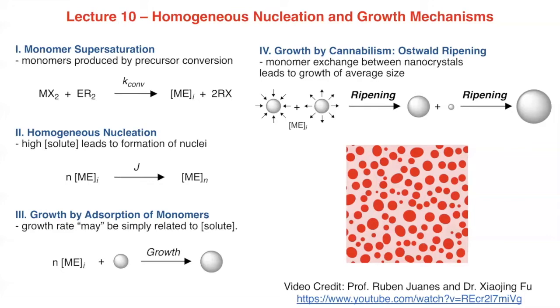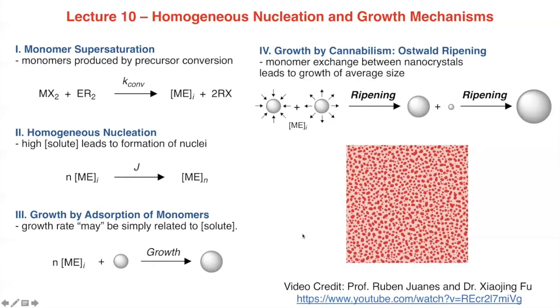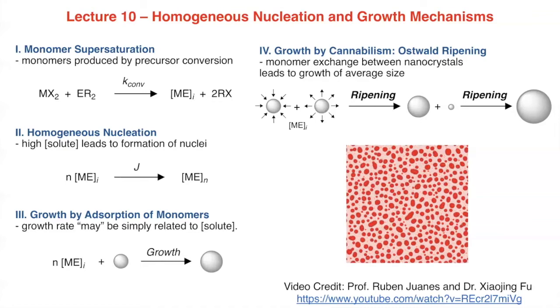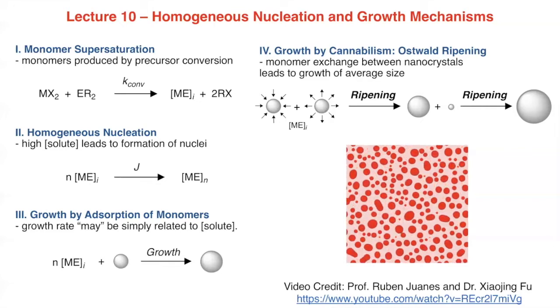And so this Ostwald ripening process is a kind of particle cannibalism, which you can see in this video here of these red droplets phase separating. Slowly you'll see small droplets disappearing and the larger ones growing. Occasionally you'll see two droplets fuse, an aggregation type of a mechanism. But the simple picture is the exchange of monomers as soluble units between the crystals.